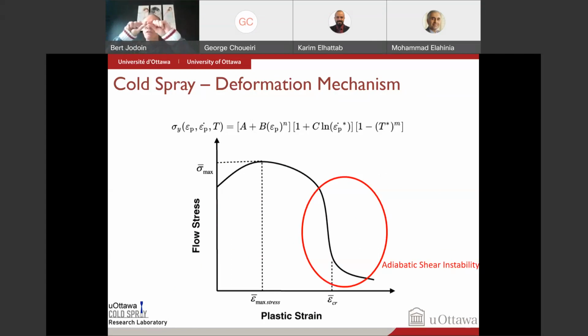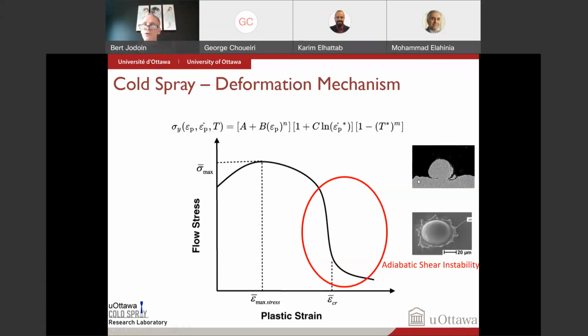At the bottom of the particle, that first layer is deformed so quickly that you're going to get lots of heat generated, and the material is going to warm up, and then you're going to get an abrupt reduction in your flow stress, and that tiny layer will start to flow almost like a liquid. So if you throw your particle slowly, you're not going to get that, but if you throw it fast enough, you're going to get into this zone where you have lots of energy that's converted into heat very, very locally.